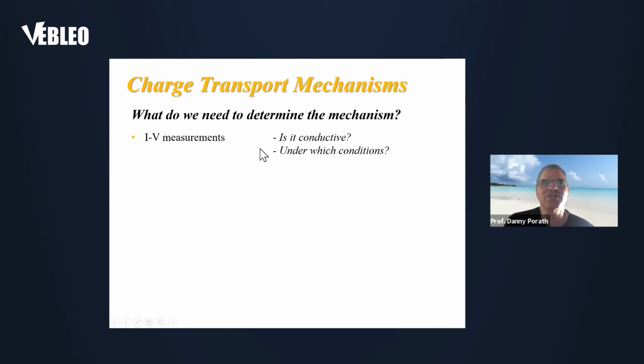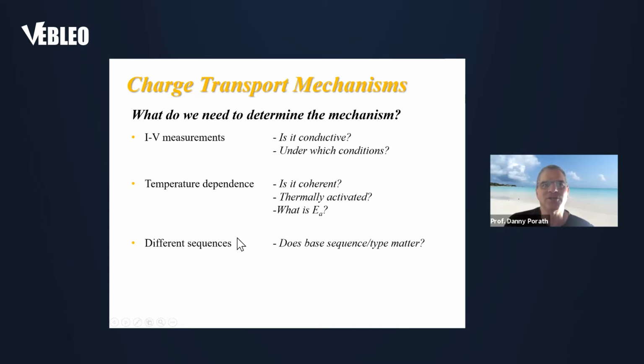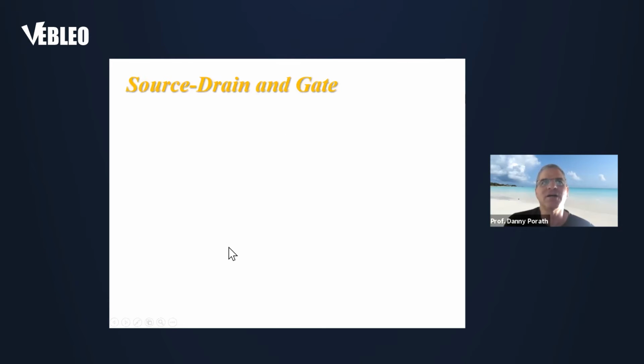So the first information would be current-voltage (IV) measurements that will tell us if the molecule is conductive and in which conditions. The temperature dependence can tell us if it is coherent or incoherent, if it is thermally activated, and what would be the activation energy. And if we use different sequences, it will tell us if the base sequence or the type of bases is important for this mechanism. And finally, gate measurements, that I will immediately explain, will tell us if the contacts are good, if we have charging effects, what's the density of states, and so on.